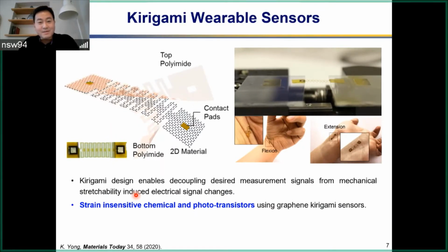But here is the device that we built. It's very simple. It's a very thin polyimide, about 2 to 4 micron thin, controlled with the spin coating. On top and bottom is sandwiched, and then in the middle, you have a graphene pattern exactly the same way as the polyimide. So this is the simplest structure that we have built, and you're seeing on the left our image.